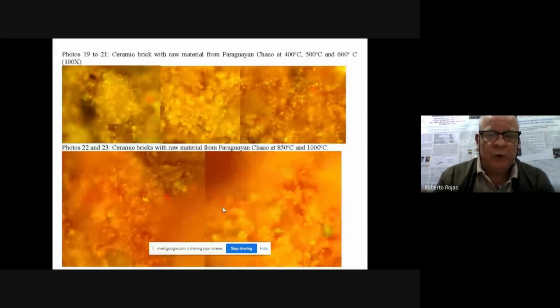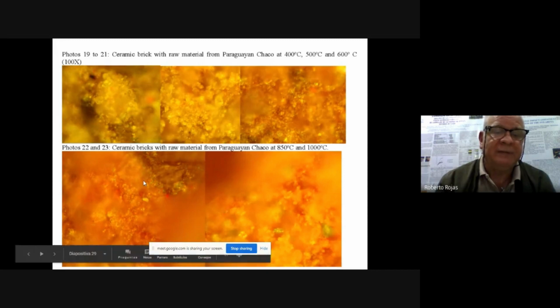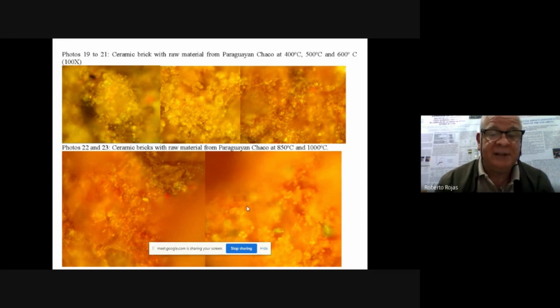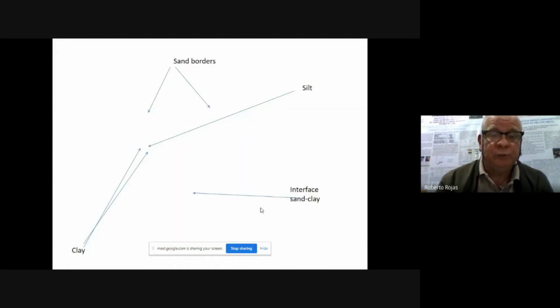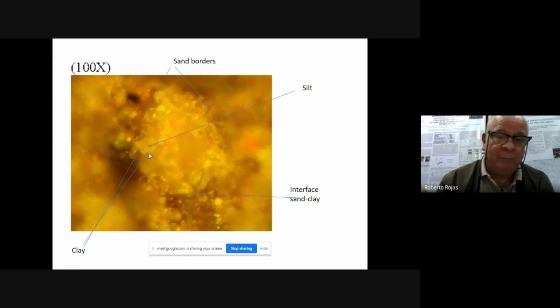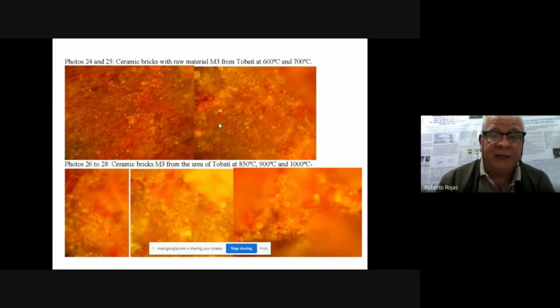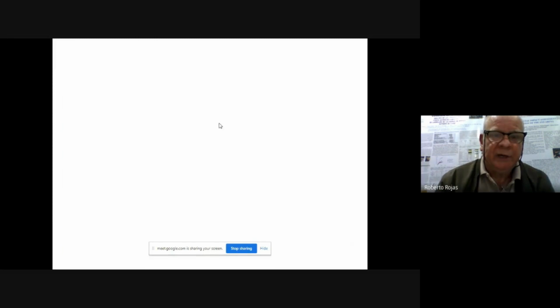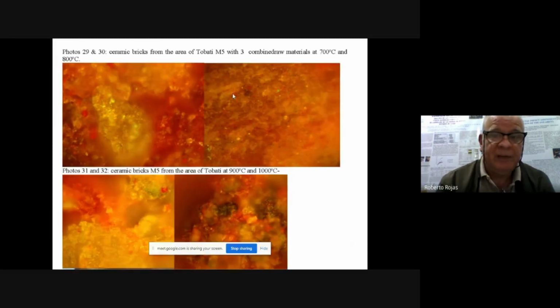These were what was seen at about 400, 500 degrees, 600 degrees, 800, 900, 1,000 degrees. And we're going to show that these smaller parts are clay, these a little bit bigger are silt, and the sand borders are around here. This was a metallographic microscope we used to see this. This is a sample of Tobatí M3, then M5 with a mixture of the three components of Tobatí raw materials.